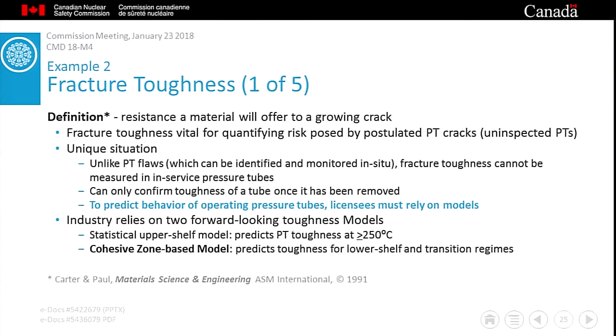Fracture toughness is a key input to pressure tube risk assessments, like leak before break and fracture protection. However, since toughness can be measured only once a tube has been removed from the reactor, licensees need another way to get the values they need for doing risk assessments. So they rely on models, which predict tube-specific fracture toughness values based on a number of parameters. As we'll see in the next slide, temperature is one such parameter. Because pressure tube toughness differs considerably over two temperature ranges, industry has developed separate models.